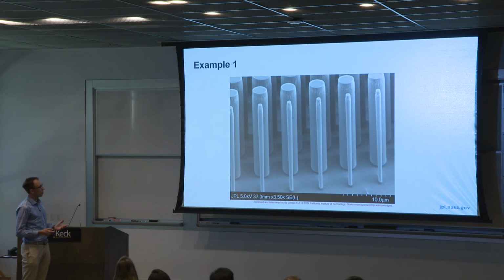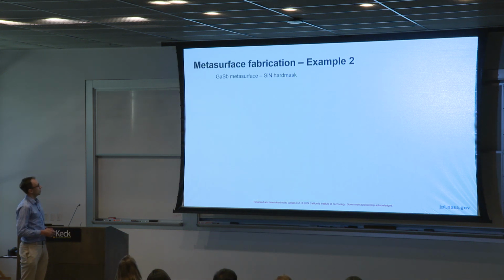So if you're not tolerant to that, you have to do something different, because this comes from the fact that your etch mask, your photoresist, has eroded while you did the etching. That's something that is hard to completely get rid of using photoresist. You can try to mitigate it, but completely reducing it using photoresist is difficult. So one way to mitigate that is to use something called a hard mask.